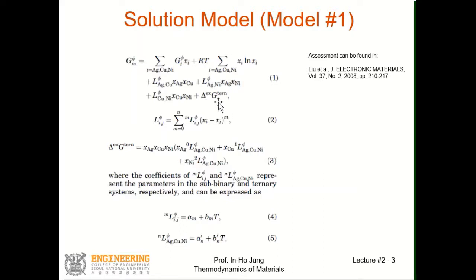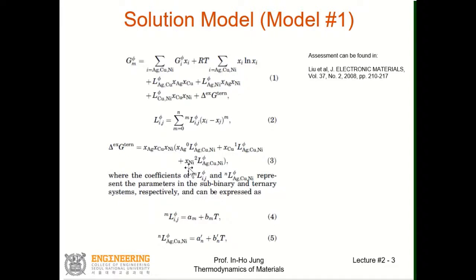The ternary excess term is expressed by mole fraction of Ag, Cu, and Ni to the power 1,1,1. The L0 parameter is connected to an additional power of 0 in Ag, L1 is connected to the additional power of Cu, and L2 additionally depends on the mole fraction of nickel to the power 2. So these three parameters are used to describe the ternary excess parameter.